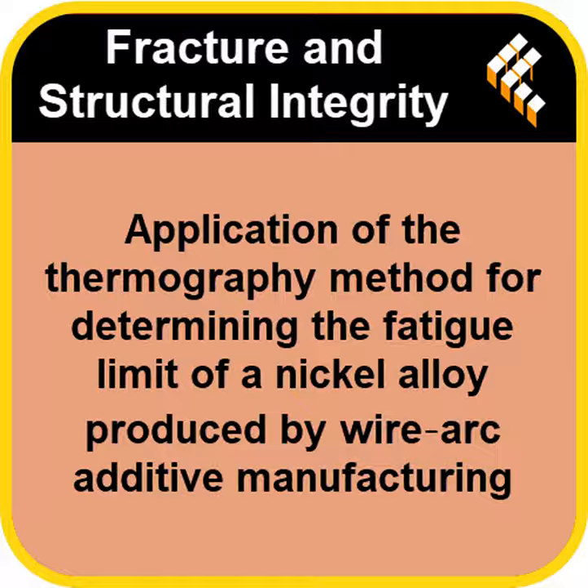They decided to use the rate of temperature increase, that's called theta dot, right at the start of the block. They focused only on stage 1. They never even waited for stabilization. That's the shortcut. So instead of waiting for the temperature to flatline, they just measured that immediate spike. It's like flooring it in a car and only measuring how fast the speedometer needle jumps in the first second, not waiting to hit your top speed. That's a perfect analogy. It's pure efficiency.